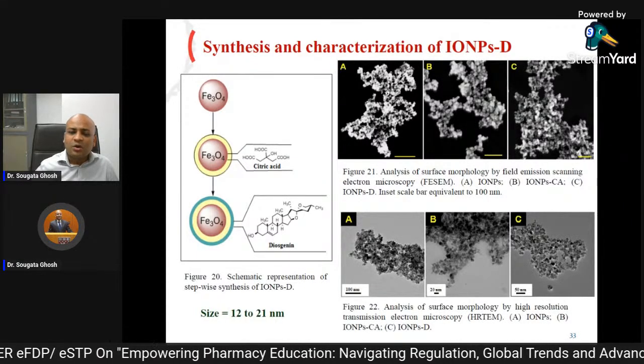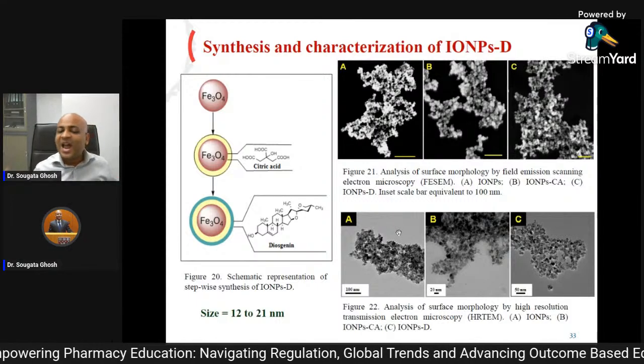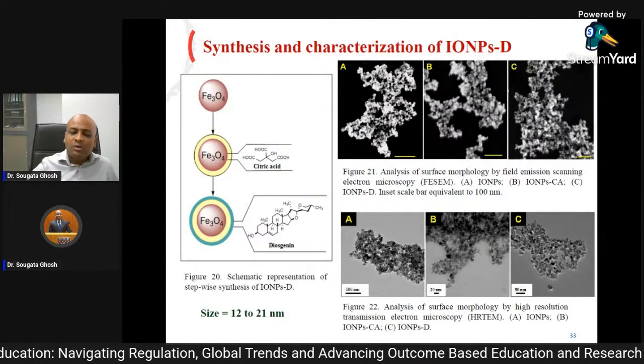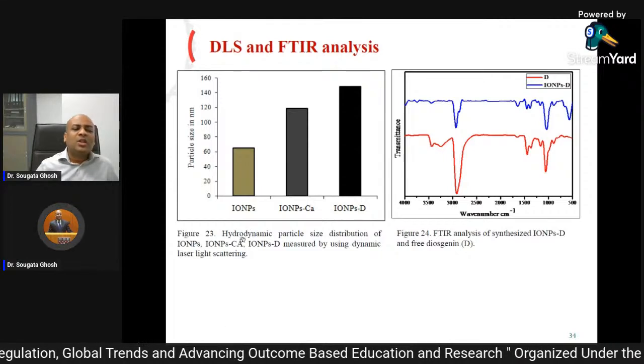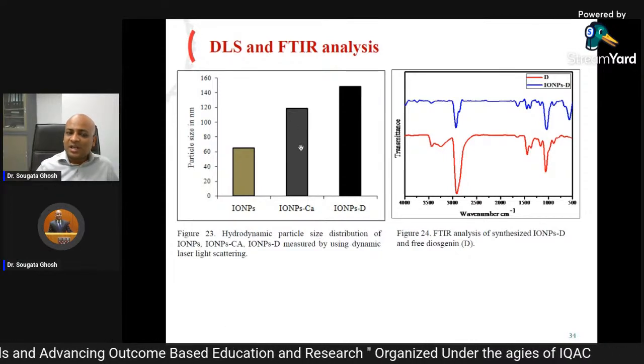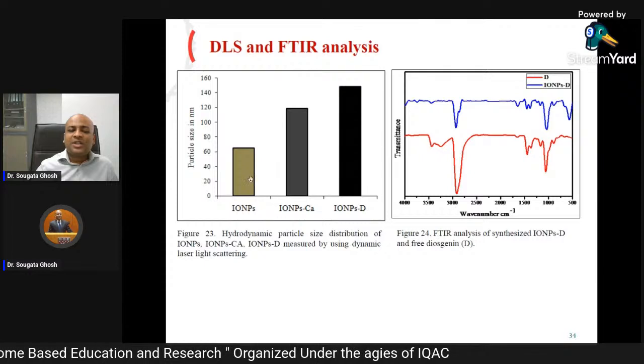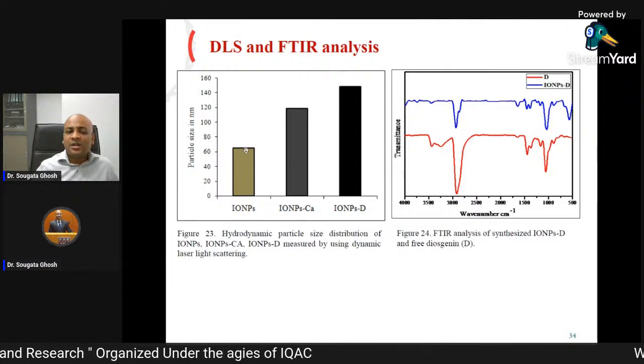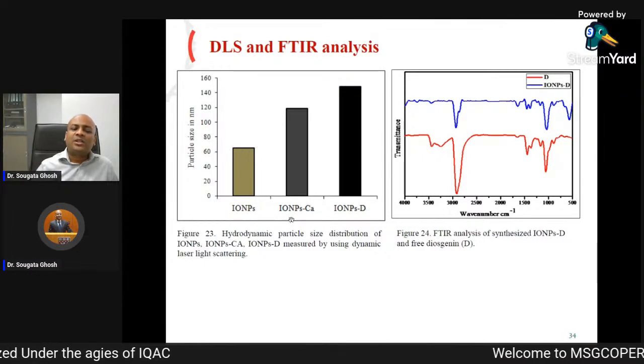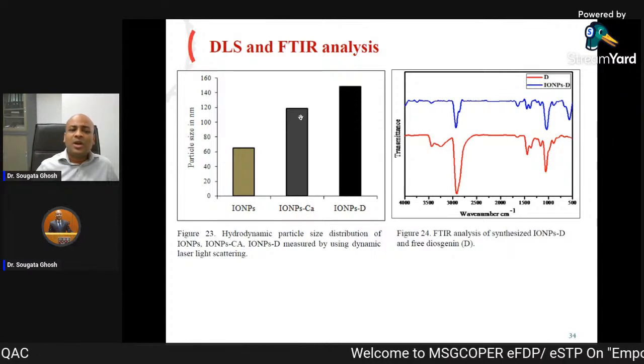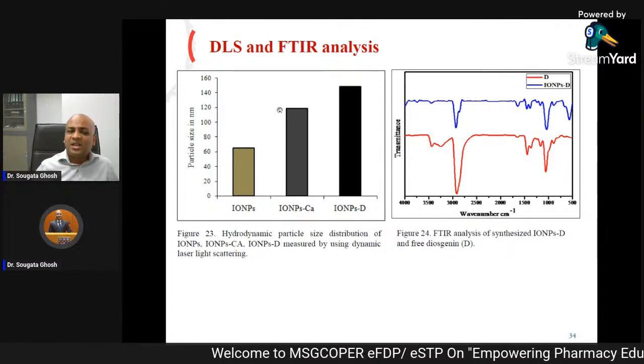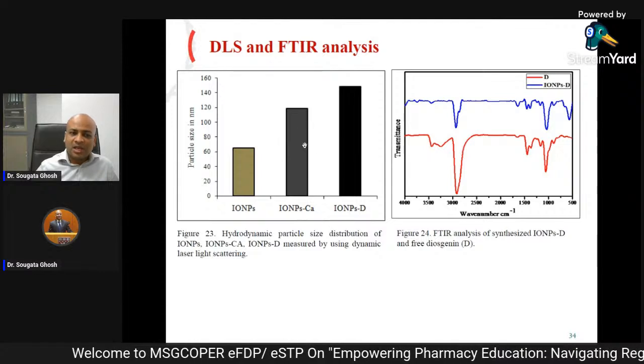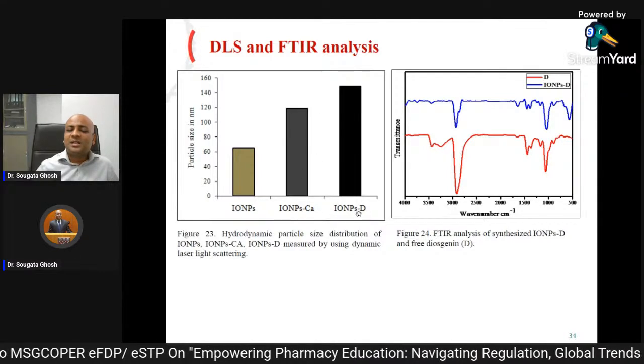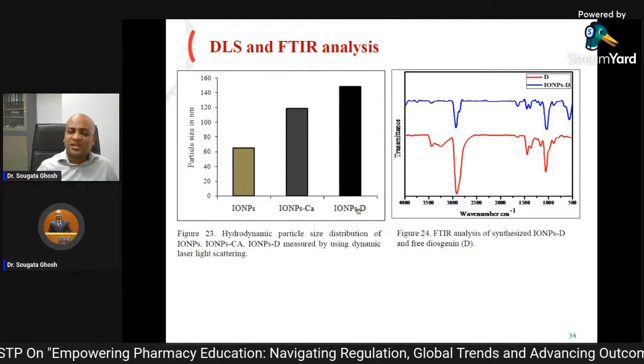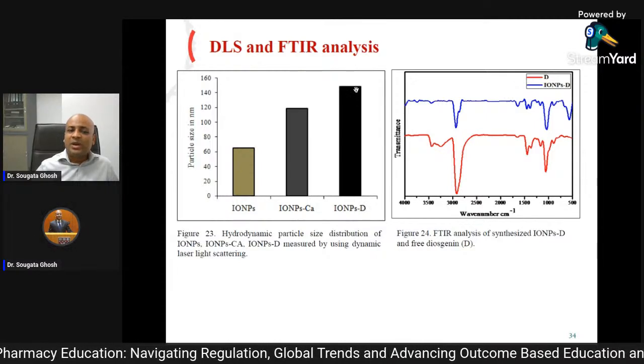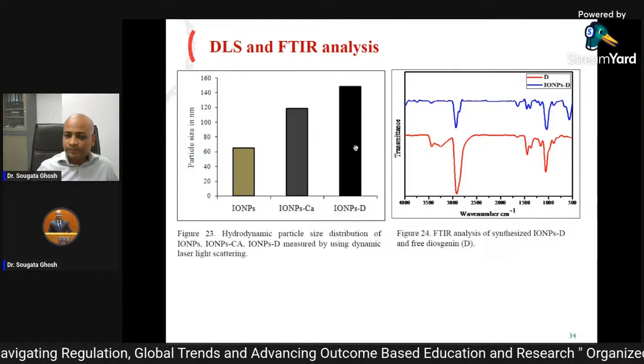Now, why are they together, why are they not free? Because they are magnetic. They attract each other. That's why they are always in clusters. So we saw the hydrodynamic size of the clusters, and only iron oxide nanoparticles were around 65 nanometer, the clusters. Iron oxide nanoparticles with citric acid were around 119 nanometer, the cluster size. Iron oxide nanoparticles with citric acid and diosgenin, they are around 145 nanometer.